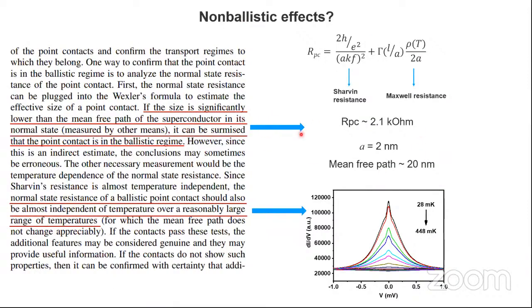The first one is that the contact diameter should be much smaller than the mean free path, so that we are in the ballistic regime where spectroscopy can be done. The electron does not dissipate energy otherwise.